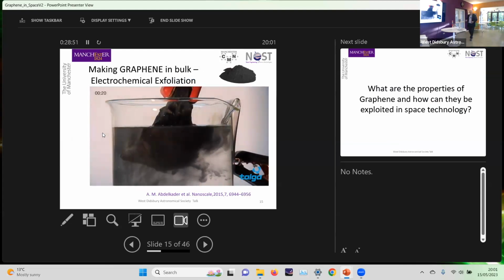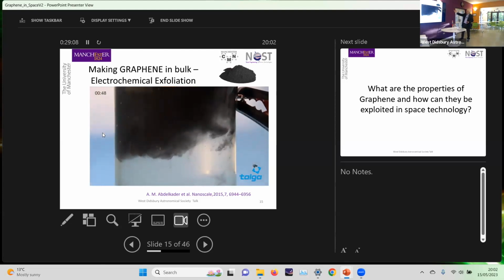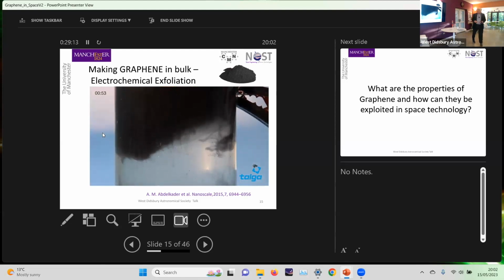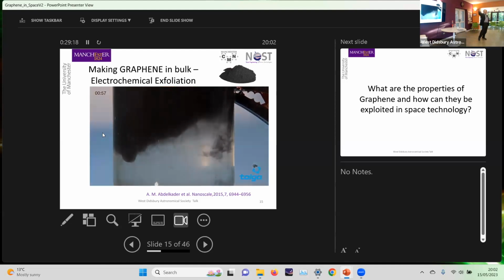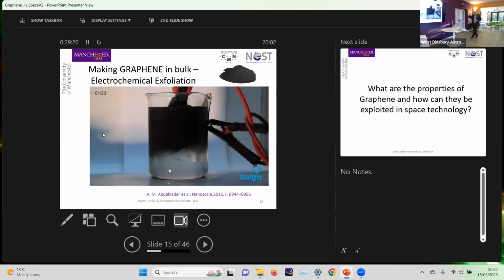Of course, it would be nice if that were just the top layer that was peeling off, but we can't control where that is. It could be anywhere in that structure. So there will be some heavy lumps of graphite that come off, as well as some multi-layer graphenes and some single-layer graphene. You can see the heavier stuff falling there under gravity. And of course, if we centrifuge it, then we can increase that effect. And so we can take off all the light stuff, all of the nice powder, as it were.